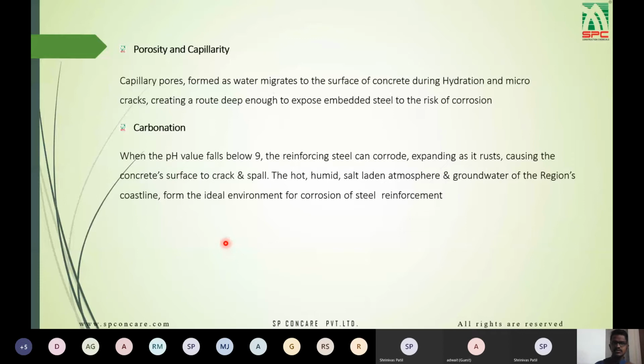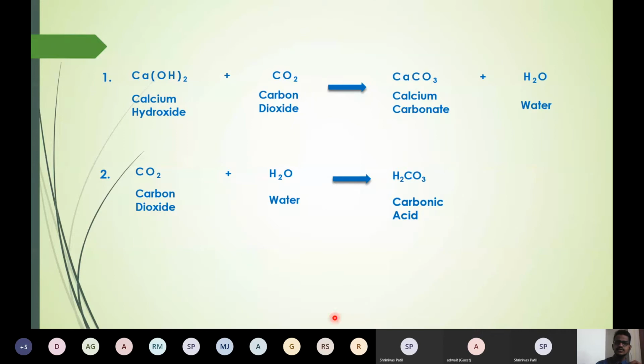So suppose we take an example of carbon dioxide. Now suppose this CO2 enters through that porosity into the concrete. So what will happen? As per the first reaction, as I said, the reaction of dicalcium silicate and tricalcium silicate produces calcium hydroxide. Now, when this CO2 is in contact with the concrete, the CO2 and calcium hydroxide react with each other, ultimately forming calcium carbonate and water.